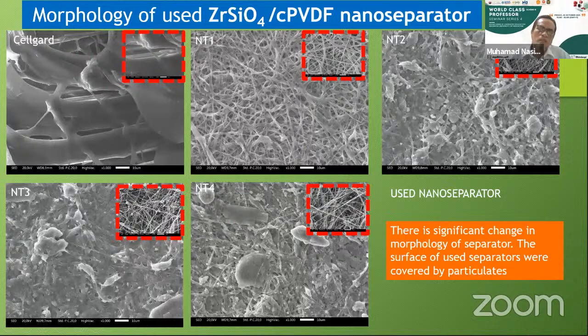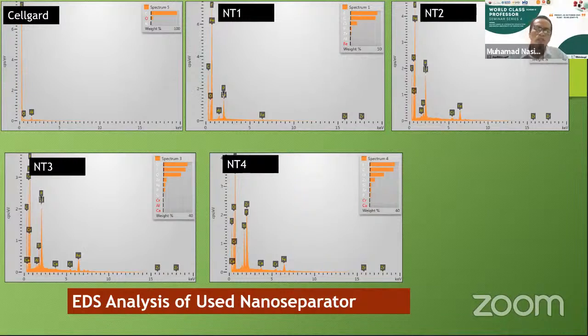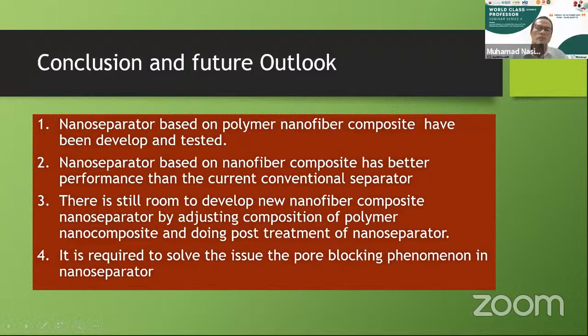And then we study the morphology of the separator after we use it. You can see here this Celgard separator. This is new separator. This is after we use it. This is new separator, and this is after use. And in the case of the composite, you can see here this new separator. This is after we use it. We can see there is particulate on the surface of the separator. We think it will influence the porosity and pore size of the separator. And then we observe the composition of the used separator. The result is here. And then conclusion and future outlook.